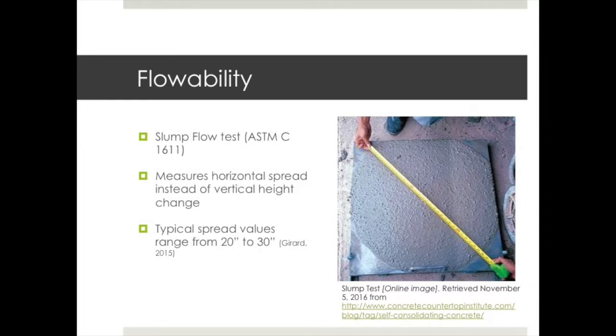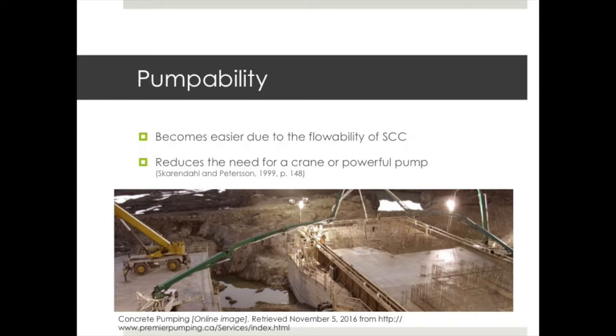A typical test to measure the flowability of SCC is the slump flow test, which measures horizontal spread. Typical spread values of 20 inches to 30 inches demonstrate SCC's high flowability. Due to this high flowability, it becomes easier to pump the concrete, especially bottom-up pumping. This reduces the need for a crane or a powerful pump.